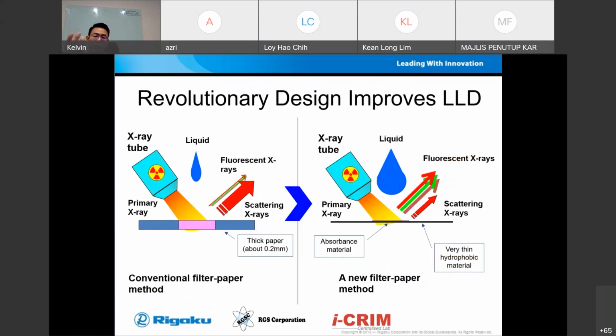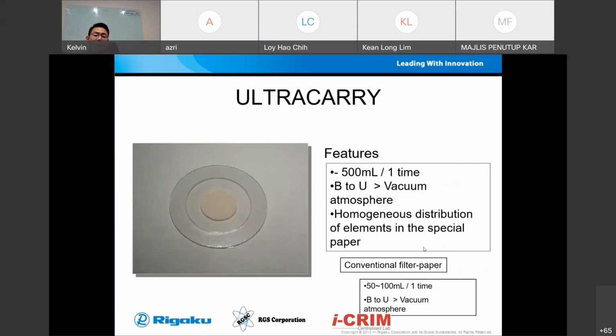So in the conventional filter paper, firstly, it is very thick, which contributes to the background. Compared with this Ultracarry itself, it is very thin. Another very important thing is that even though it's thinner, it allows you to absorb more sample, like 500 milliliters, compared to the conventional filter paper, which only allows 50 to 100 milliliters at one time. So here we achieve two important aspects to improve the LLD: one is we can measure more volume, and secondly, we reduce the background.